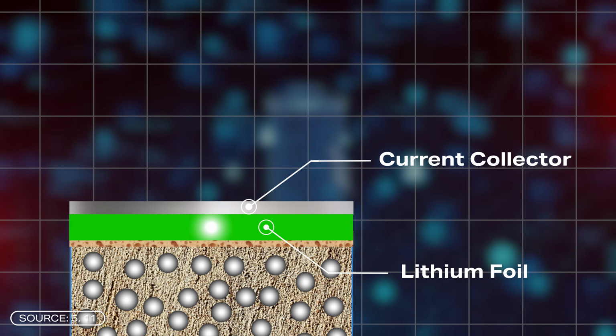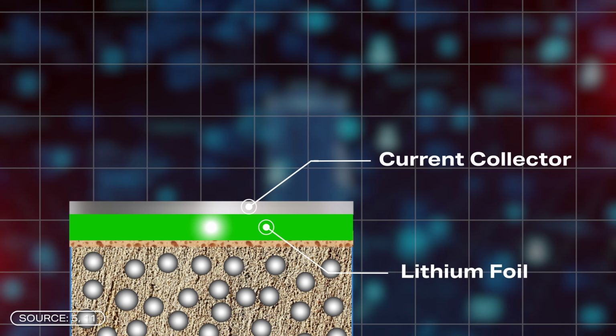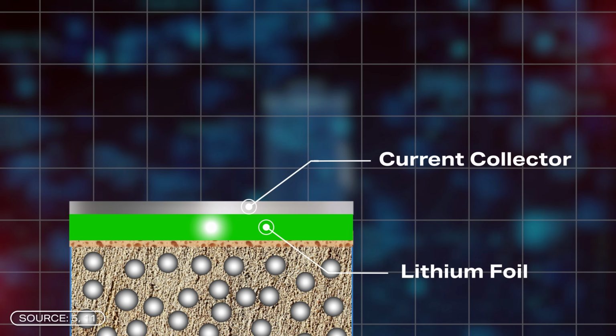To prevent all of this, the solution is to use lithium anodes that are as thin as possible, or rather a lithium foil. But that's not so simple. The manufacturing process is quite complex and above all very expensive. The lithium foil must be applied to the current collector, but because lithium is so highly reactive, very specific conditions are required, and that's not so easy. So the lithium anode is causing battery manufacturers and researchers quite a few problems.